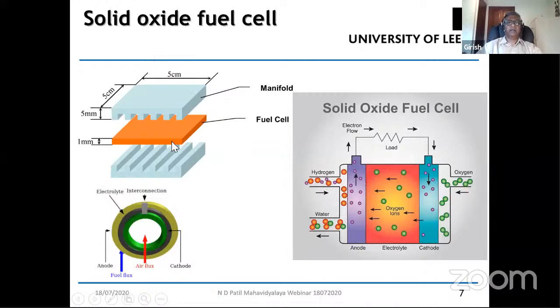And the fuel cell, because it's an electrochemical device, has a cathode, an anode, and a separator of cathode and anode, which is a solid electrolyte. Now, a solid electrolyte is an ion conducting membrane. So it could be a proton conductor, or it could be an oxide ion conductor. In this particular schematic diagram, all the three components of the cell are assembled together in almost a 1 millimeter thick flat surface. So you have cathode, anode, and an electrolyte sandwiched together between the manifolds on top and the bottom, which are basically carriers of oxygen and hydrogen.